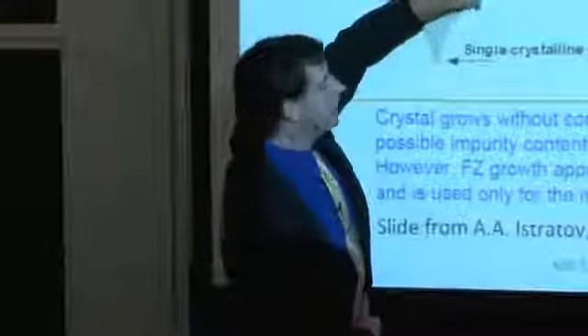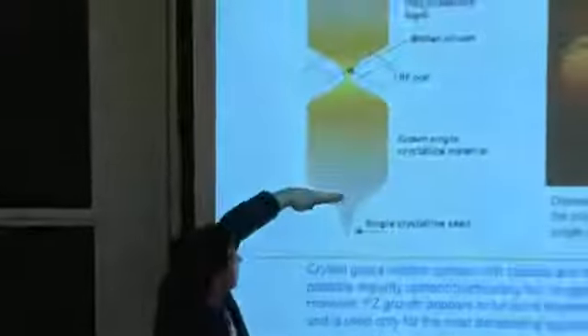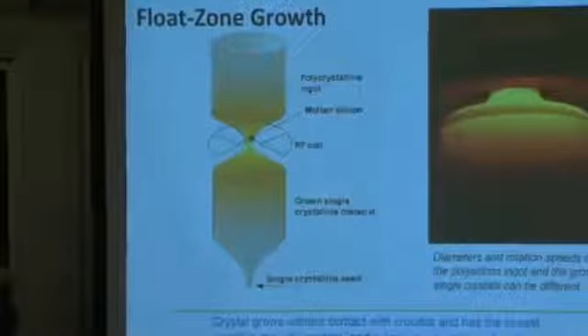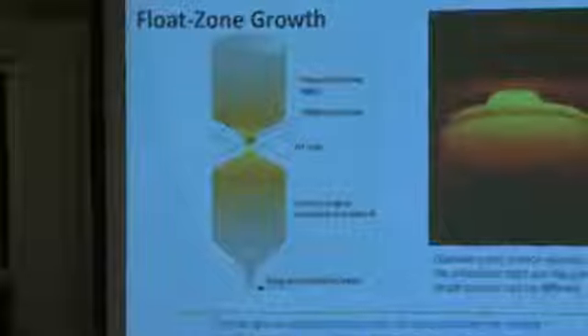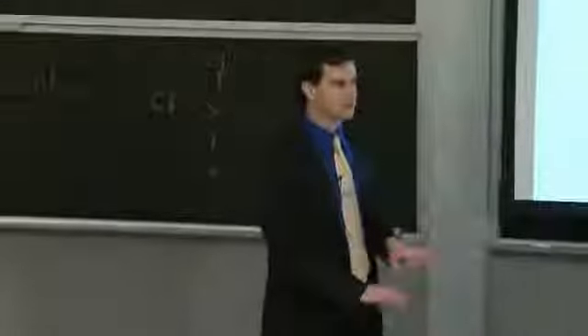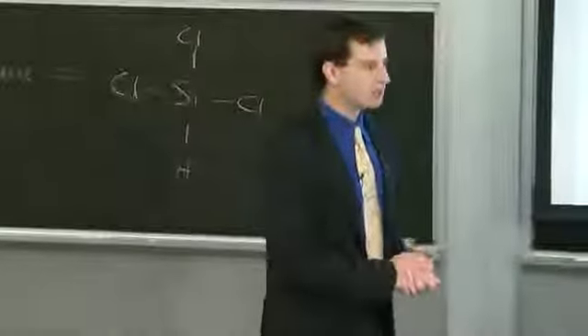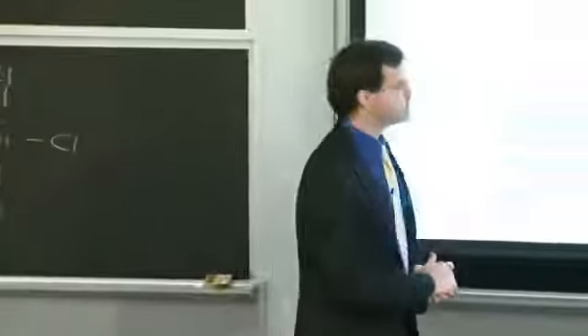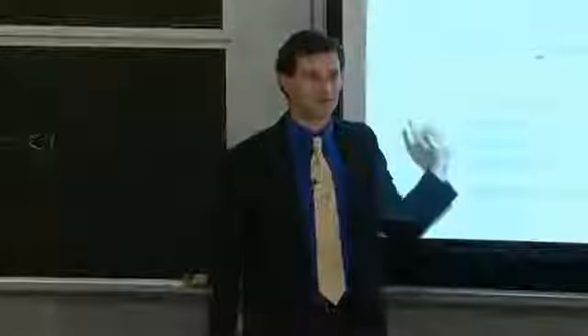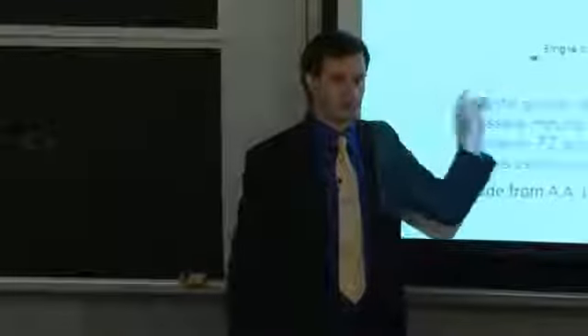And in the process, it concentrates the impurities in this liquid region. Since the impurities have a higher solubility in the liquid than they do in the solid, they are aggregated inside of the liquid region. And again, like a comb, they just get swept out of the material. Not all of them, but a large percentage of them. And so you can make multiple passes with this RF coil to further concentrate the impurities on the extremities and remove them from the material. So that's the float zone method. Very expensive material, very high purity.